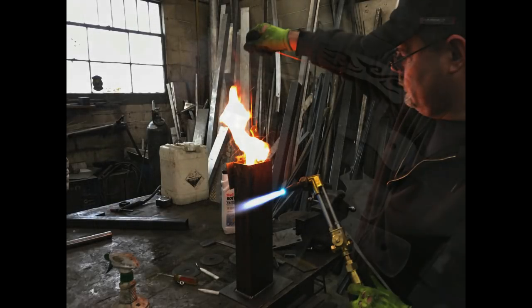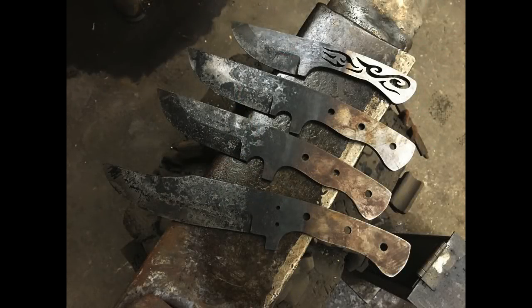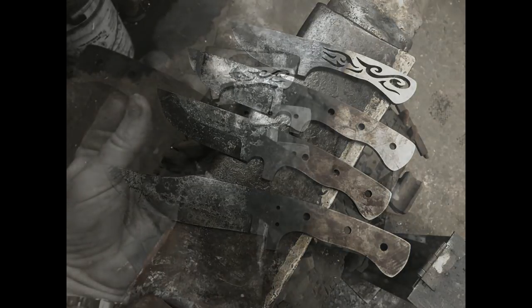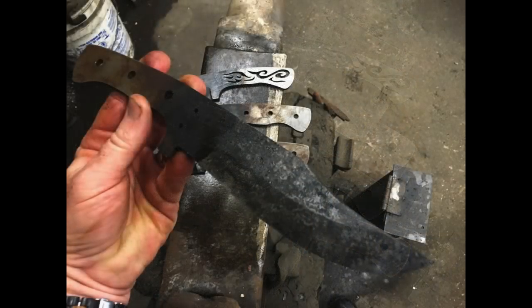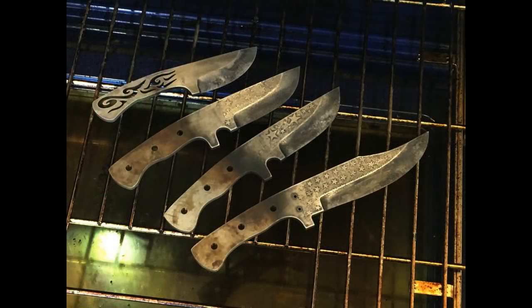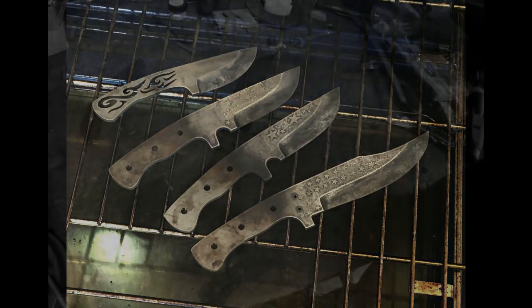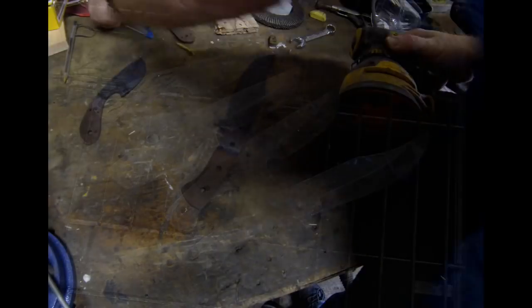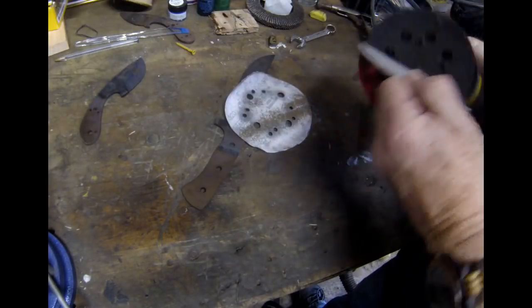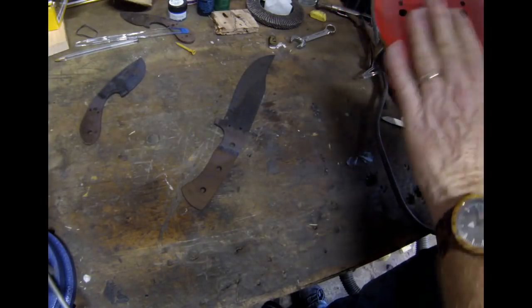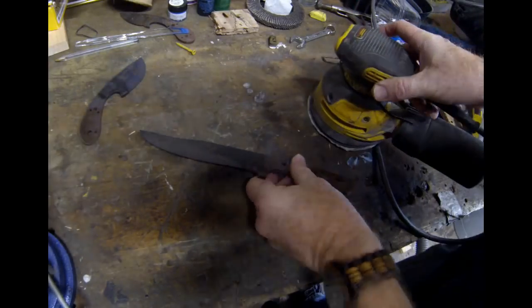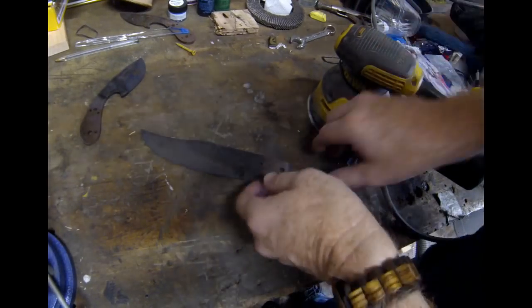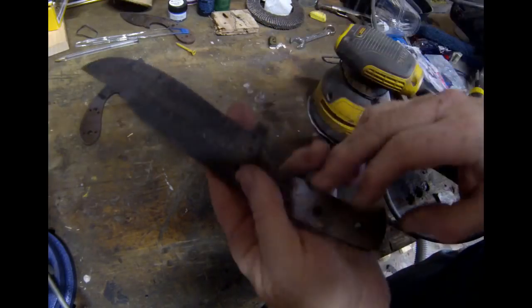So the heat treating process, my friend Jason heats up the blades with an oxyacetylene torch. He heats them up until they're cherry red, non-magnetic, and then quenches them in oil. This results in a nice Rockwell. Usually we end up with a Rockwell 58 on the C scale. After that, I throw them in my wife's oven, 375 for 3 hours. Then I turn off the oven and I let them cool overnight as a tempering. It makes the blades less brittle. So now they're hard and less brittle.